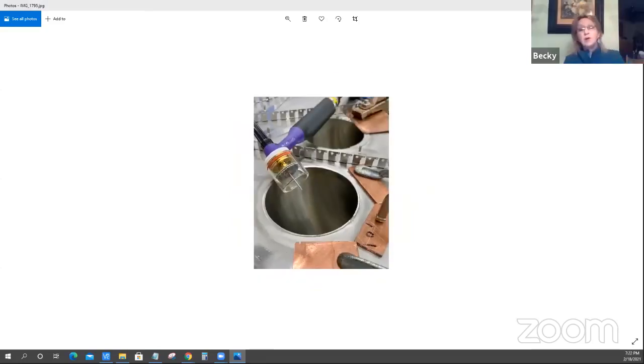So this is my setup for a cryogen vessel flange for a different code over at NASA Goddard. They had bought this and someone shipped it, and it was cracked, and I had to repair that. And the tubing coming through was a lot thicker than the flange. So I had to put up some copper heat sinks all around it. And I had to use a lot of argon too. Argon shields the metal, because if you don't shield it with argon, it'll get oxidized and contaminated, and then it will crack.